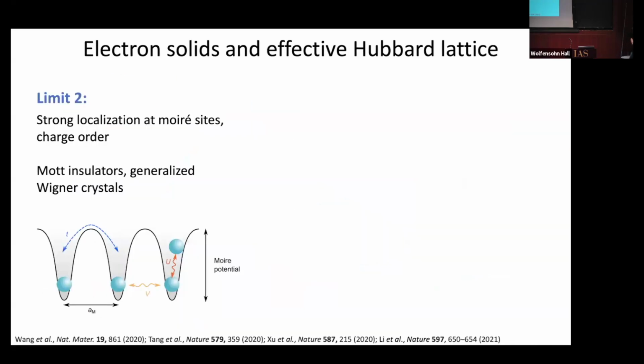There's a second limit, which I didn't really talk about at all yesterday, which is the case where your Moiré potential is extremely strong, and it actually tends to localize your carriers at particular real space sites of the Moiré superlattice. And in general, this is the situation that is often realized in these transition metal dichalcogenide systems. So you can think of the picture in the simplified cartoon where you have some Moiré potential. It may be very deep. It's deep enough such that carriers really like to sit at particular sites. You still have some probability of hopping between these sites. There's some on-site large Coulomb repulsion U, and of course these are still electrons that are making up the system, so you also have some extended long-range repulsion V that you get.